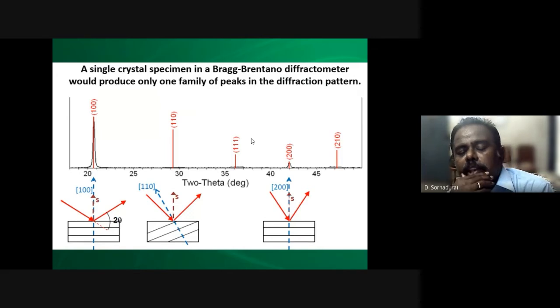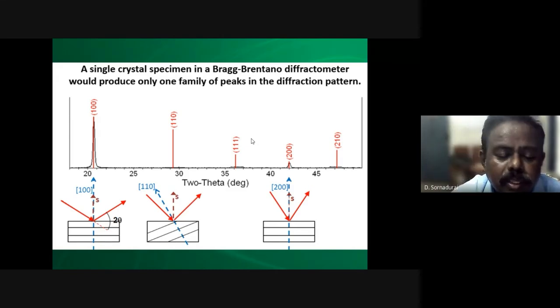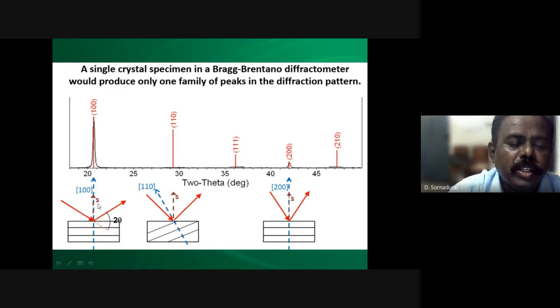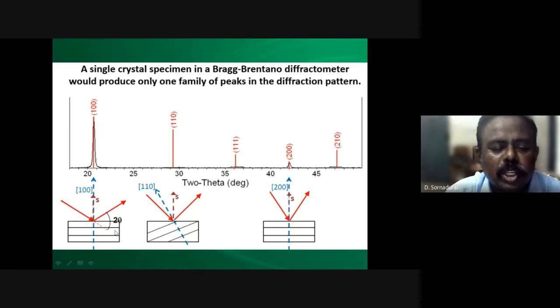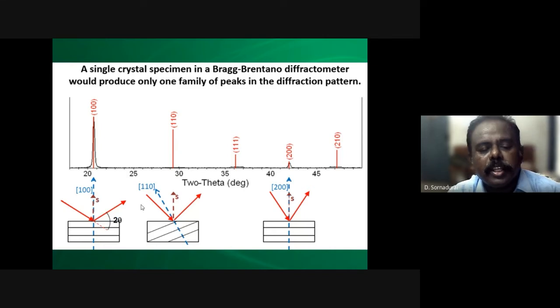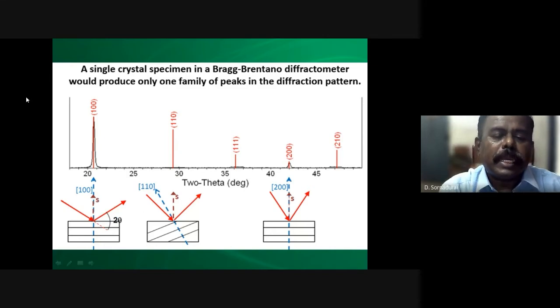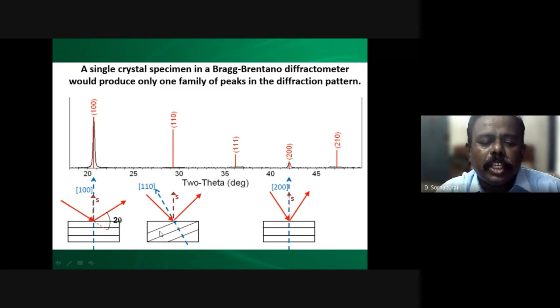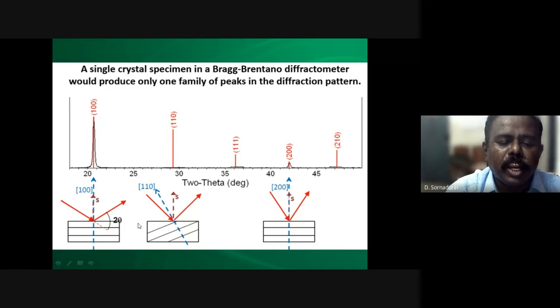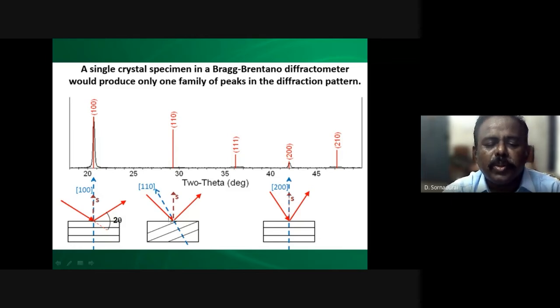So why is this arising? This peak is not coming up in the single crystal. Just see, this is well oriented along the 100 direction. That is, this horizontal plane is the 100 plane, Miller indices hkl equal to 100. Then its orientation direction is 100, so the 100 peak has come. Whereas if we take this 110, it is still straight, without any bending, and it is like this 100. So there is no back scattering from this, and that's why it's not appearing here.